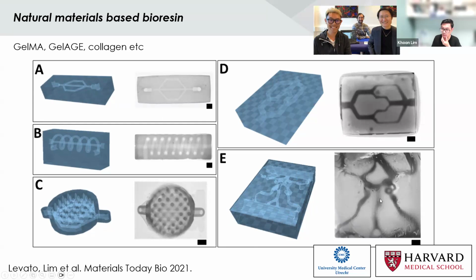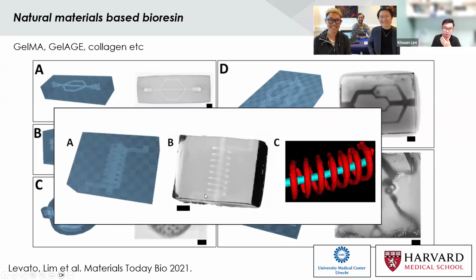If you try to perfuse through it, you can see a bubble form here because the blood vessel is kind of truncated. And these are all open and hollow. So you can perfuse two different kinds of liquids, and you can see from this CT imaging here that both of them are open. And this is interesting because you can continuously perfuse, and you can also look at oxygen or nutrient transfer from one channel to the other channel. And because it's all printed with hydrogels, cells can be encapsulated in the surrounding bulk. So we're bringing quite a lot of different dimensions and parameters into our cell-laden organ-on-a-chip models in this case.